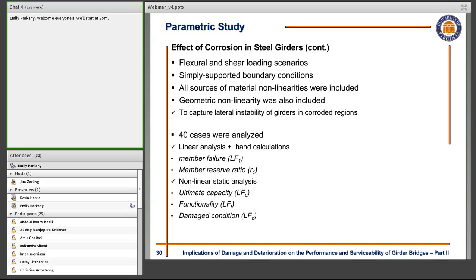Regarding the material nonlinearities, we included all sorts of material nonlinearities in the models, and all the assumptions regarding the modeling of the details of these structures are very similar to the ones that we validated in phase 2 of this investigation. And in this specific case, as we have degraded girders, there would be a potential for lateral buckling and local instability for the girders. So we also included the geometric nonlinearities into our model. So we ended up having 40 cases of analysis for both of these structures.